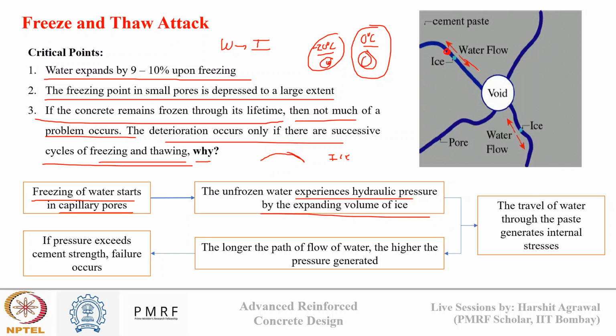Due to this, the water will experience hydraulic pressure and will start to move inside the pore system. So water will travel through the paste, and this movement of water inside the paste will generate stresses. The longer the path of flow of water, the more pressure the water will generate. And if this pressure exceeds the concrete strength, it will cause failure in the concrete. So pressure is generating, pressure is releasing, pressure is generating, pressure is releasing. In this way, over successive cycles, it will cause fatigue in the concrete system, and this will cause cracking in concrete, and it will lead to degradation of concrete.